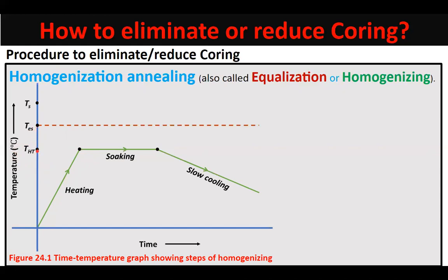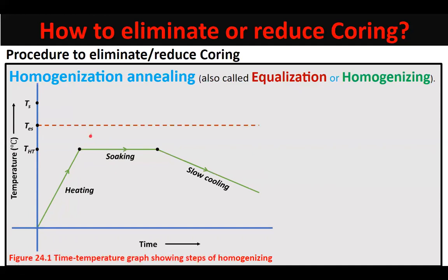And why? If by mistake you reheat your casting to a temperature close to the effective solidus temperature, it has been observed that the mechanical properties, particularly toughness and ductility of the type of alloy, get severely impaired, and the problem is called overheating.